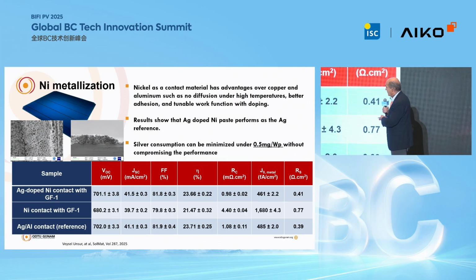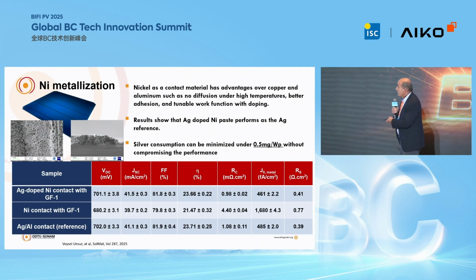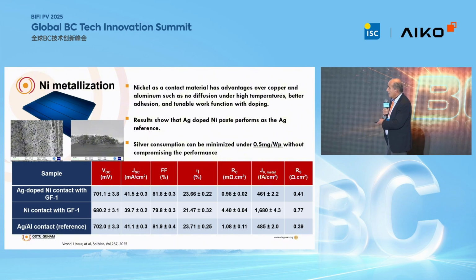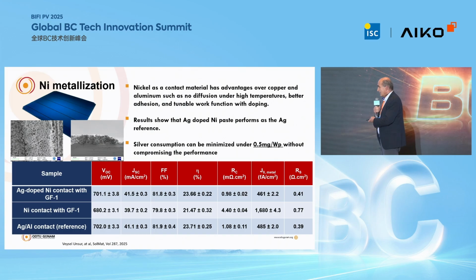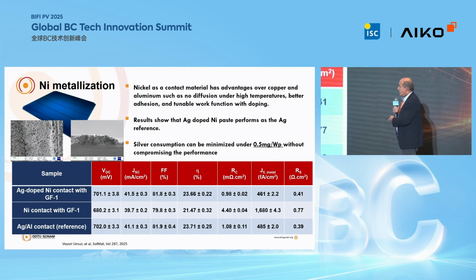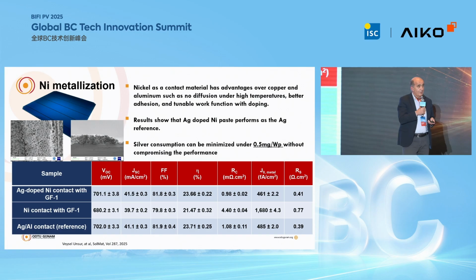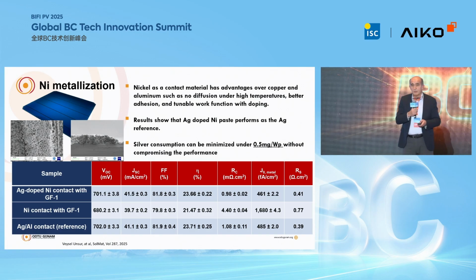In both cases, this is, by the way, a TOPCon solar cell, we have reached very similar values in the efficiencies. So it seems that silver-doped nickel is very competitive when you compare with the standard reference paste. But pure nickel is giving us a smaller efficiency, or worse values in terms of other parameters. But it is still a good number. So we can still work on this and improve it if you want to use pure nickel. So nickel should be considered by industry. It can be a good alternative to copper.